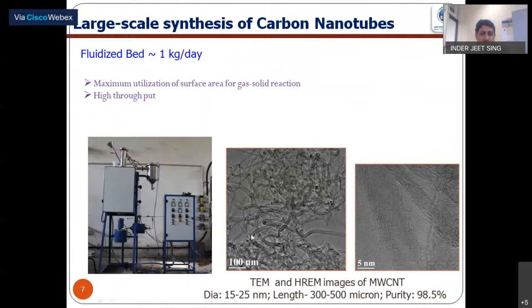kg per day. These two figures are showing the TEM, the transmission electron microscopic image, how the CNT looks, and then high resolution TEM where you can see the number of walls of CNT, and we could get reasonably good purity, 98.5% pure of the sample.